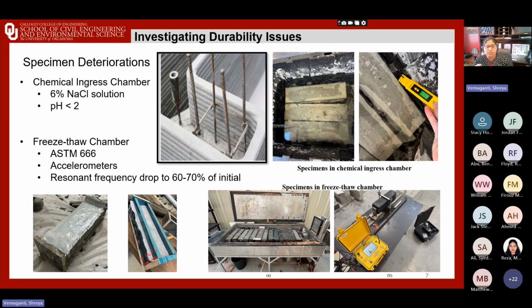So I'd like to start before just diving into 3D printing. I want to introduce why it's important to understand the role of interfaces in these cementitious systems. So interfaces, either manually created or naturally existing, they're often the weakest link in layered or just these layer on layer building concrete structures. And they could be the means to control some sort of a long-term durability aspect. So if you look at this picture that I'm showing here, this is already a 3D printed structure where reinforcement is used within, right? There are already layer by layer building happening there, which creates these naturally occurring interfaces, which become also these cold joints.